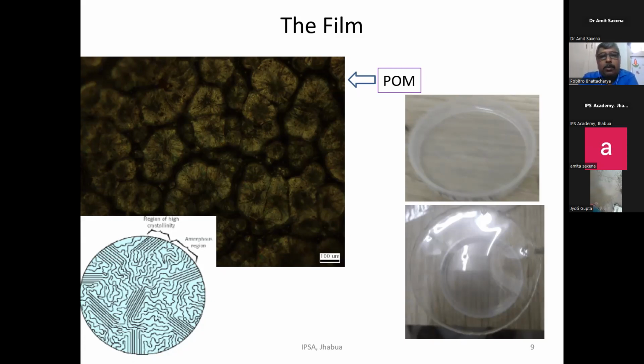But now that has been corrected, and we say that ions can migrate through the amorphous region predominantly. They do migrate through the crystalline region, but the conductivity is poor, and therefore one should focus on how we can increase the amorphicity of the polymer matrix, and reduce the size and even the number of these spherulites. Though the number is not in our control, the size of these spherulites is pretty much in our control, and we should try to reduce them.